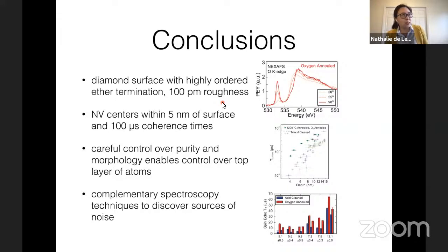Hydrogen termination is actually better in the sense that you get a less defective surface, but there's a technical problem that you get a negative electron affinity surface that gives you this charge transfer to surface adsorbates, and then that gives you band bending that destabilizes the NV charge state. So actually there is an effort in my group trying to look at NV centers under hydrogen terminated diamond in UHV conditions where you don't have this charge transfer process, where we do expect that to be a better surface from the perspective of defect density.